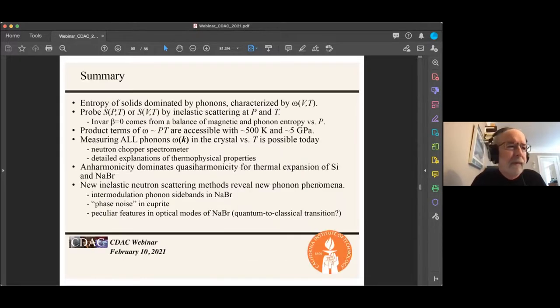Okay, so let me summarize. I'm sorry for all of the technical problems, but let me try to be efficient in saying what I wanted to say. I hope I've convinced you that the entropy of solids is dominated by phonons, and we look at that in terms of the frequency depending on volume and temperature outside of the zero Kelvin result. And we can probe these vibrational frequencies with inelastic scattering at both pressure and temperature. This is something we've done with INVAR, where we've looked at the total phonon entropy, not the individual phonons, from the densities of states.